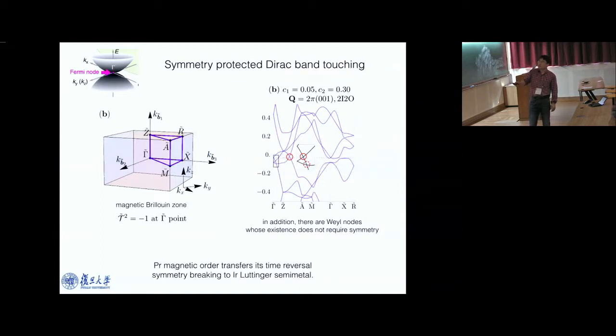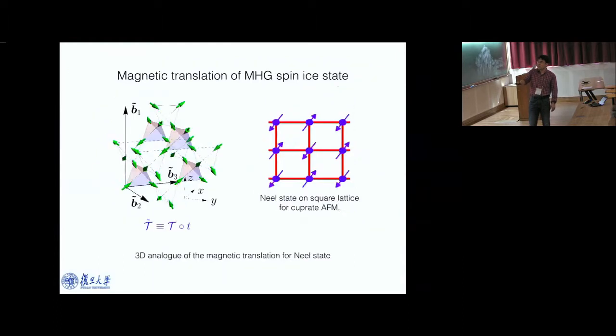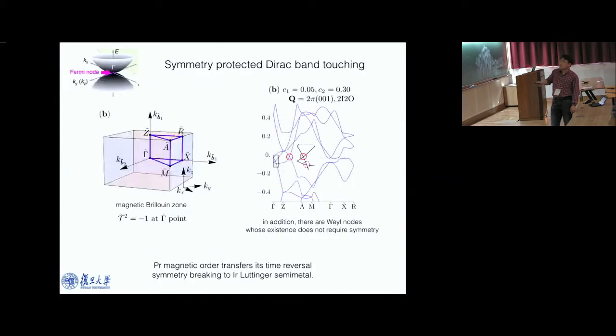So this is the reconstructed band structure in the presence of the magnetic order along high symmetry momenta. Originally there is a gamma point band touching, a correlated band touching, with 4-fold degeneracy. Now, because of this magnetic order, the magnetic order of the local moment is being transferred to the conducting electrons through the Kondo exchange between the local moment and the conducting electrons. So the conducting band structure will inherit the symmetry property of the local moment magnetic order.